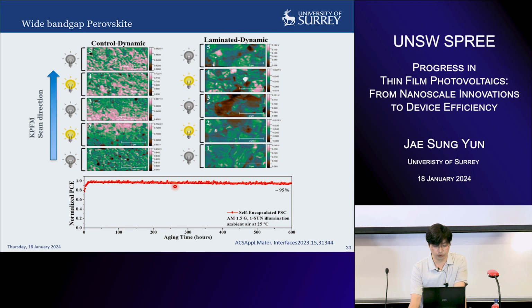And this sample shows very high stability, so eventually they are bonded together, and they call it self-encapsulation. And under the AM 1.5G, so one sun illumination, in air, the stability can be maintained up to 600 hours and only 5% of the degradation.